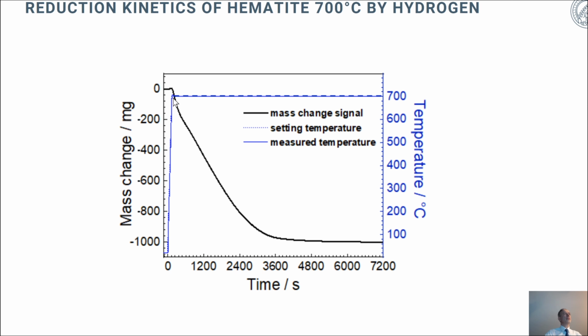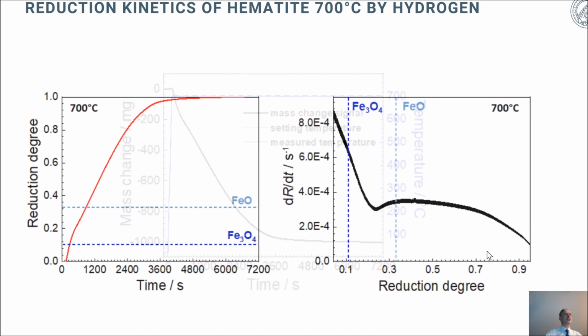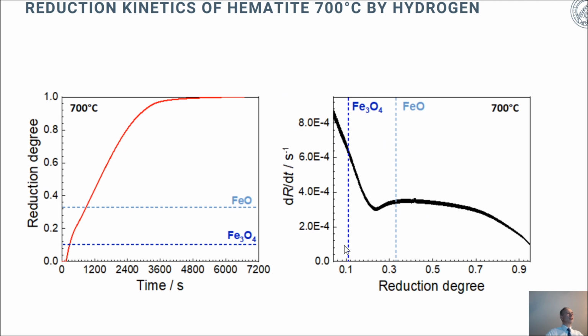And here you have the temperature range. That means we keep the temperature constant at 700 degrees centigrade and follow the mass loss as a function of time to track the reduction. When you look at the corresponding derivatives, then you can see that the reduction rate, which is plotted here on this axis, changes as a function of the reduction degree. This is a very important diagram because it shows you where the kinetics in the reduction is fast and where